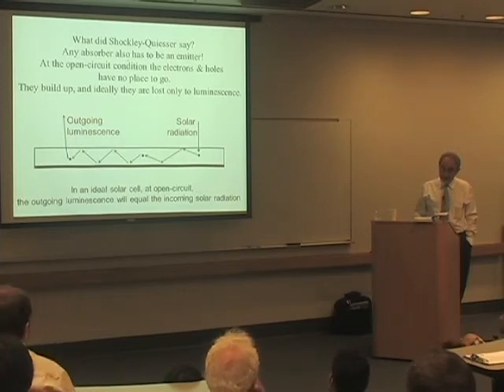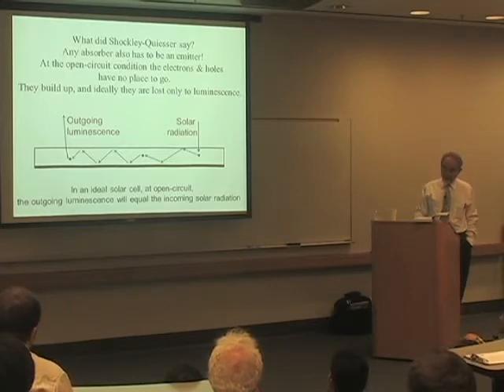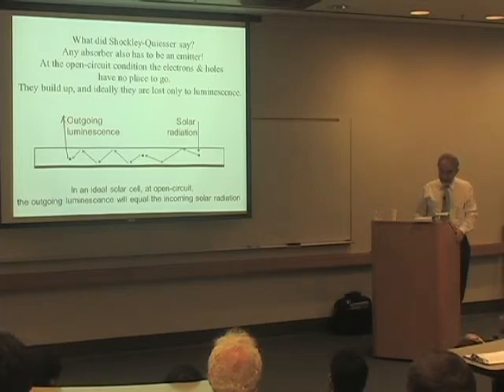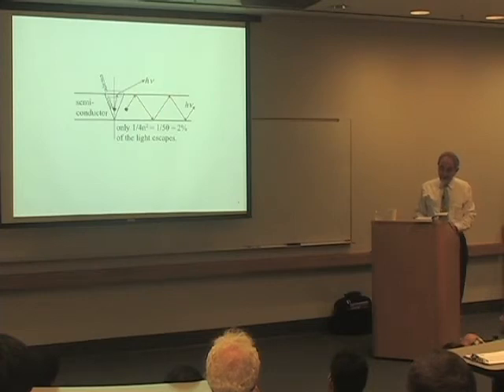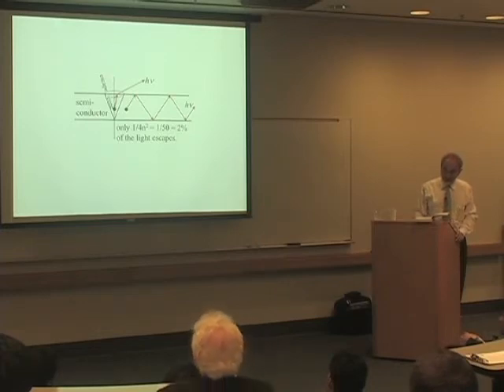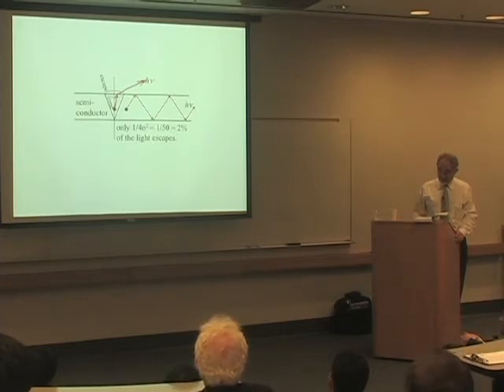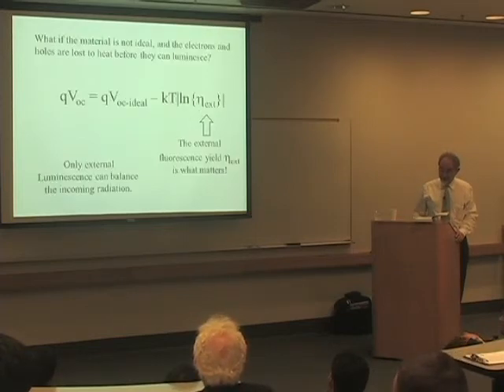It's what Shockley said. Under ideal conditions, at open circuit, the electrons and holes have no place to go, and they come back at you as 100% luminescence. And this was Shockley's condition. The outgoing luminescence was exactly equal to the incoming solar radiation. Of course, that is very rare. And the reason why it's so hard to get external radiation is that only 2% of it escapes on the first bounce, and the rest of it, 98%, could end up being trapped. So this is very unfortunate.